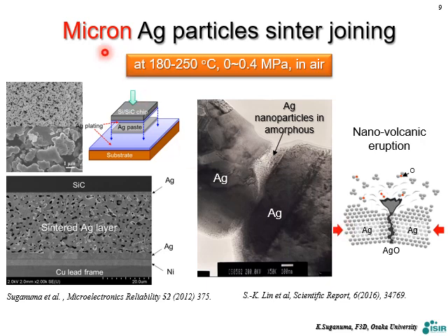So we worked on silver. Why can we make good joints even at a very low temperature like 180 degrees C at this moment, and very low applied pressure below 1 megapascal, or sometimes zero, in the atmosphere? These are the starting materials, very large and submicron. And we got this microstructure, a microporous silver layer. This has very high strength, is heat resistant, and has high thermal conductivity, very stable. Even at 180 degrees C, we can get this microstructure. So that was a big question: why can we get this kind of sintering network?